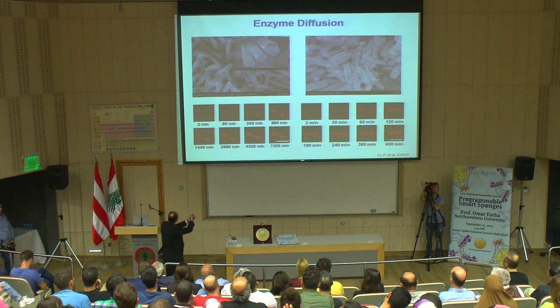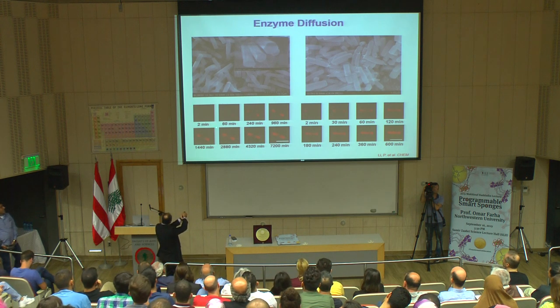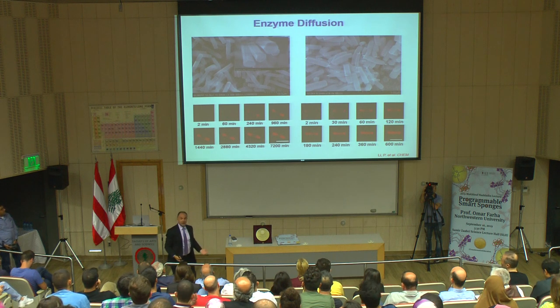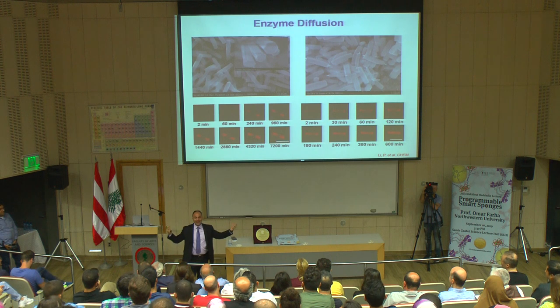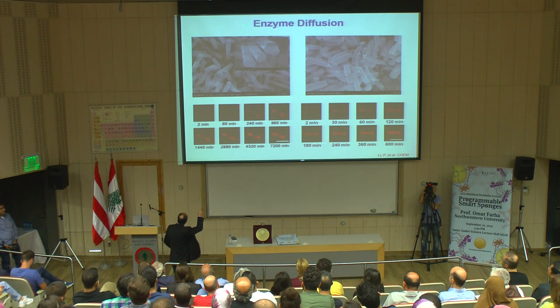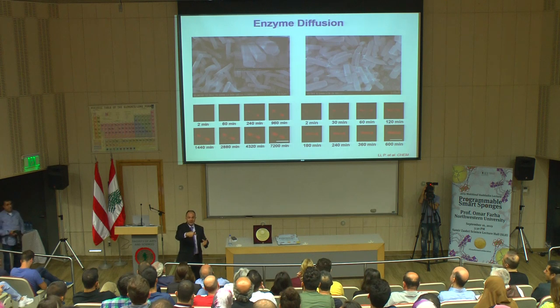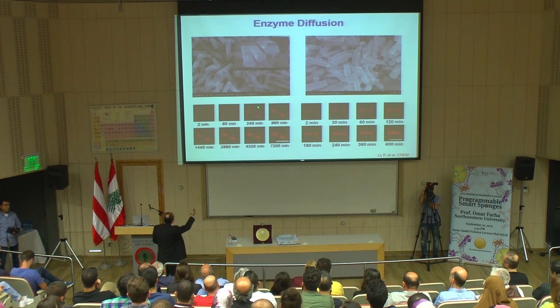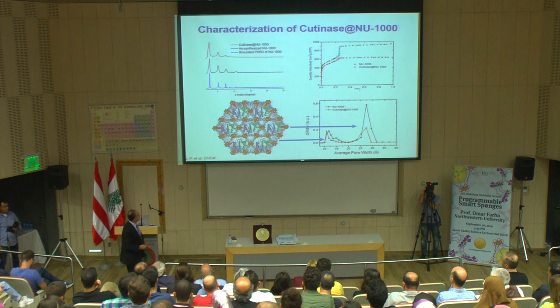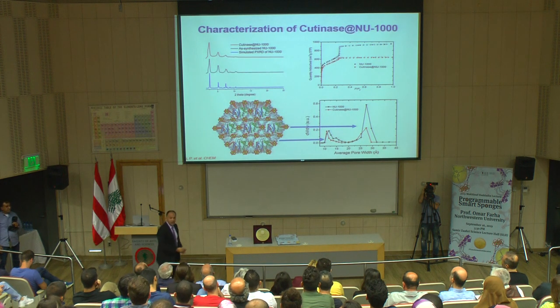One thing you should pay attention to is that the enzyme is only diffusing from the two ends, but not from this side. And the reason for that is because the large hexagonal channels only start from the ends of those crystals and not from the sides of the crystals. The sides of the crystals are the windows which the enzyme should not fit, and you don't see it moving this way. It's only moving in this direction.